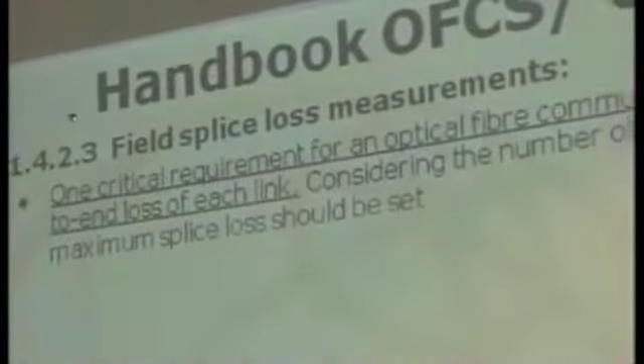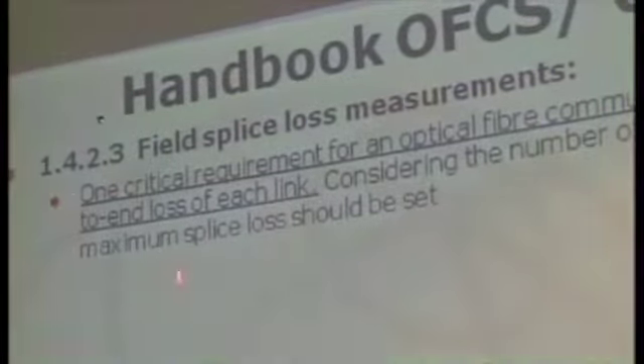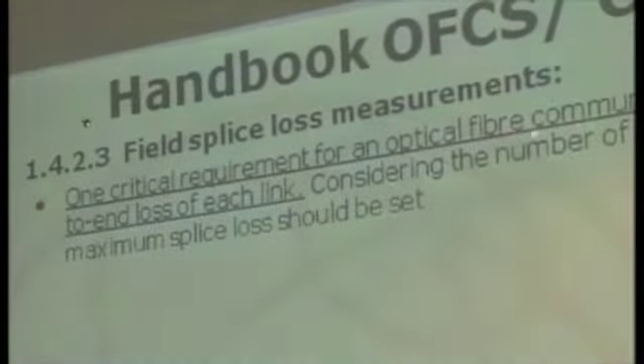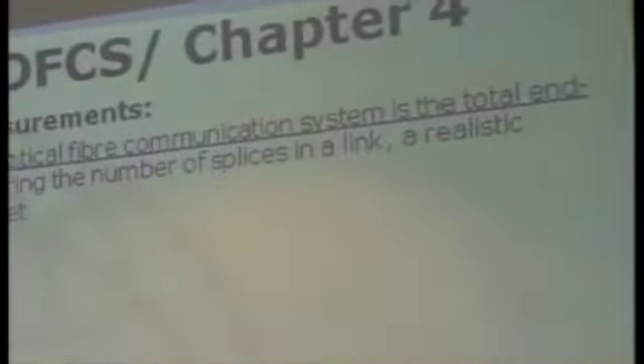As we have splice loss, it's necessary to measure. There are a lot of recommendations that could be followed by the people interested in a well-controlled network. The first critical requirement for an optical fiber communication system is the total end-to-end loss of each link. Then, considering the number of splices in a link, a realistic maximum loss value should be set. The main point is to control the attenuation of the link. The splice is part of this attenuation, but it's more important to control the attenuation of the link than to control the value of each splice, by fusion or mechanical.